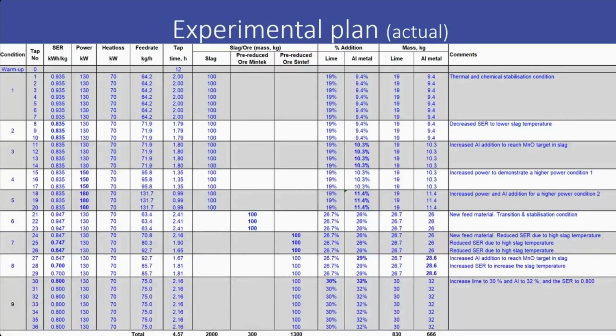This is the overview of the actual experimental plan that was executed. The first 20 taps were smelting the high carbon ferromanganese slag. The first condition was basically thermal and chemical stabilization, and then further adjustments were done to the SER so we could get our target temperatures. We also had to adjust the aluminium addition.